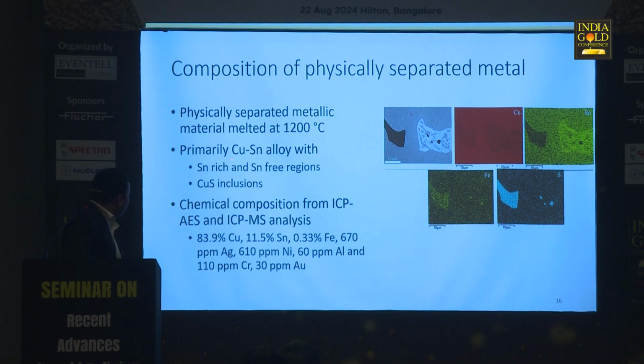Microscopically there are copper rich regions, and then there are tin rich regions, and then there are those dark spots which are essentially sulfides. ICP analysis has been performed, both AES and MS, and it shows about 84% copper, 11.5% tin, then there is some iron, 670 ppm of silver, and then about 30 ppm of gold.